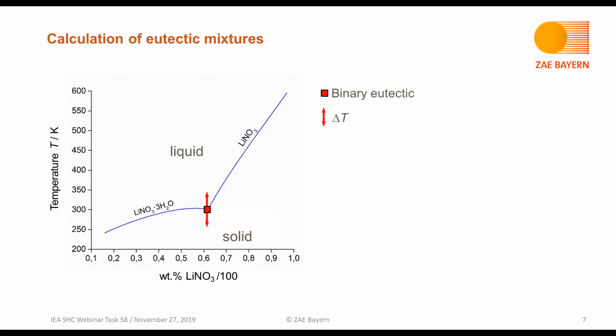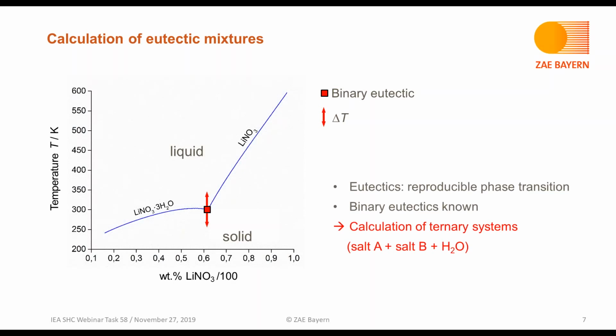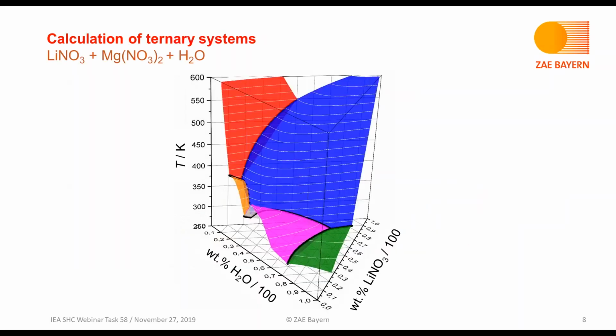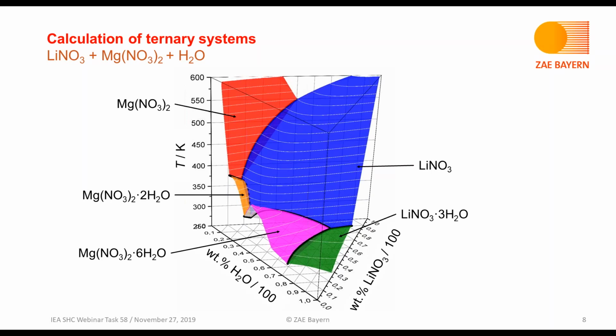If we would, for example, cycle it or use it in the temperature range that is shown here, then we can expect a reproducible transition from solid to liquid and vice versa, and this in a short temperature range. So eutectics, in theory, have a reproducible phase transition, and as binary eutectics, as the example shows, are mostly known, our approach is to calculate ternary systems containing 2 salts and water. In the case of ternary systems, the example given here is lithium nitrate and magnesium nitrate in water. Now we have different liquidus surfaces in this diagram.